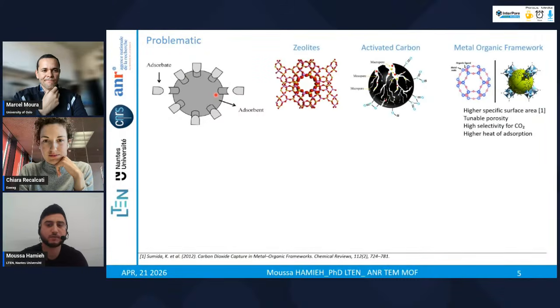There are in the literature many physical adsorbents that are very well known, like the zeolites, the activated carbon, and the metal organic frameworks. Here we will focus in this presentation on the metal organic framework, the MOF. So first, let's define what the MOF is. They are microporous solid materials. They consist of metal ions connected with each other with organic ligands. They are known for their high specific surface area, also for their tunable porosity. So by changing only the composition of the MOF, the metal or the organic ligand, we change the porosity to adapt it to the suitable application that we want.